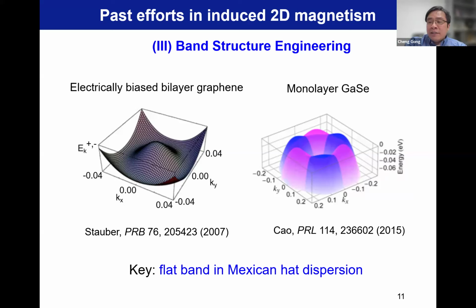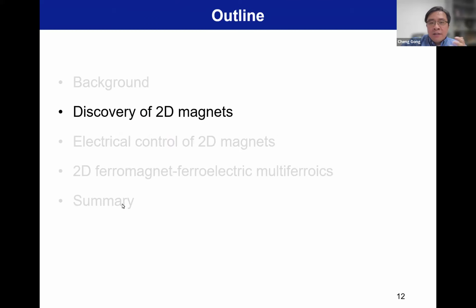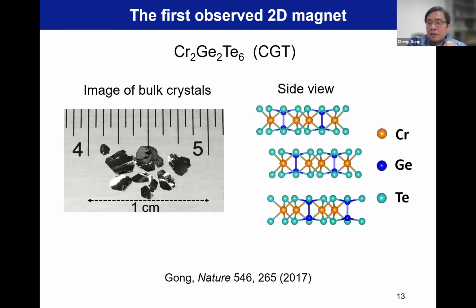But anyhow, either way, you can see it's very hard in experiment. You need to find such a material and then drive or park your Fermi level at that band edge, at that position. So in early days, I did not see success, but especially in recent years, in trilayer graphene interfacing with hexagonal boron nitride, magic angle twisted bilayer graphene, in many such systems, we saw proven ferromagnetism. So in early days, what I did was based on intrinsic magnetic crystals. I will quickly show this result, I mean, show the methodology we use.